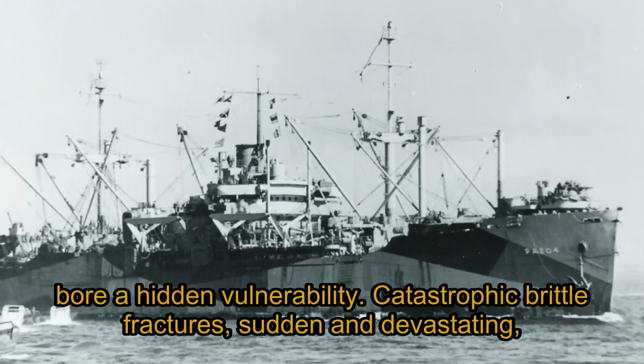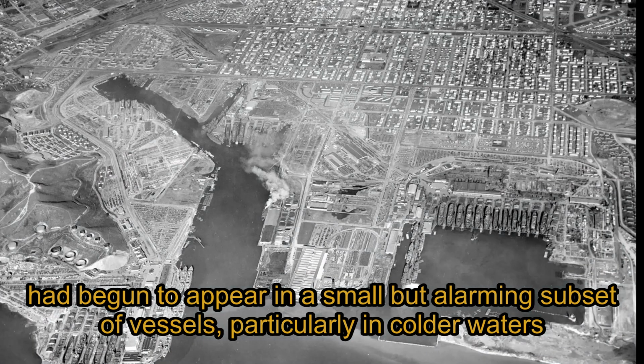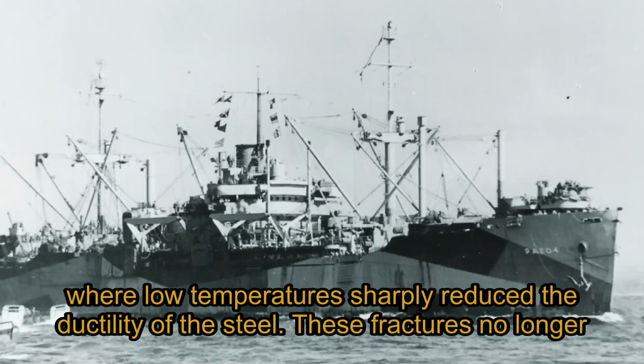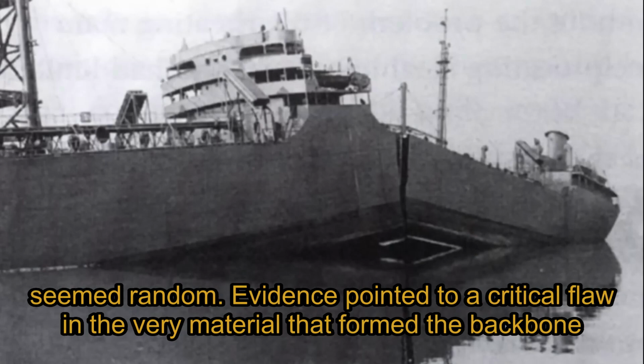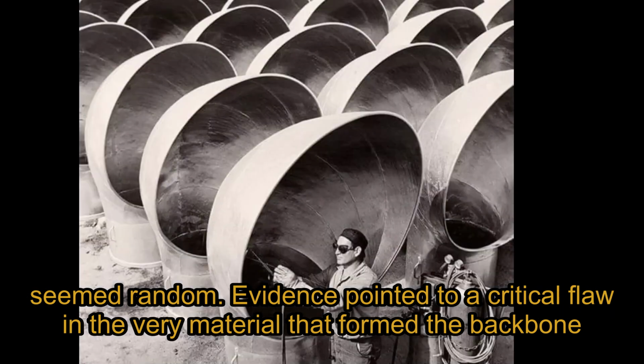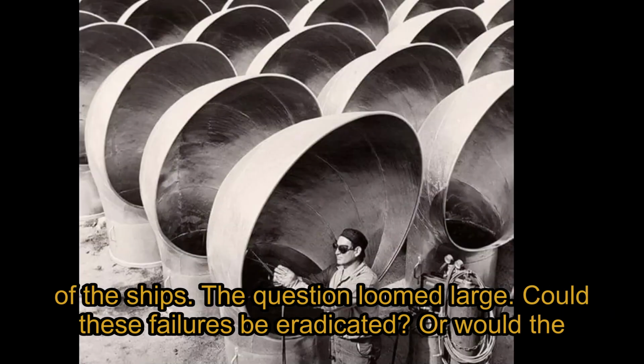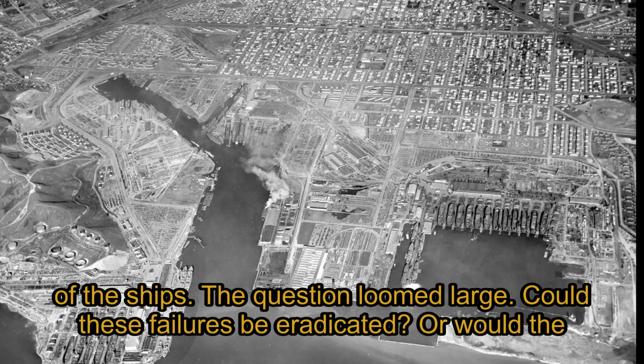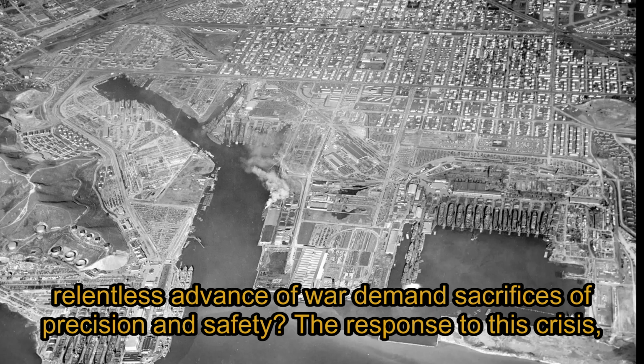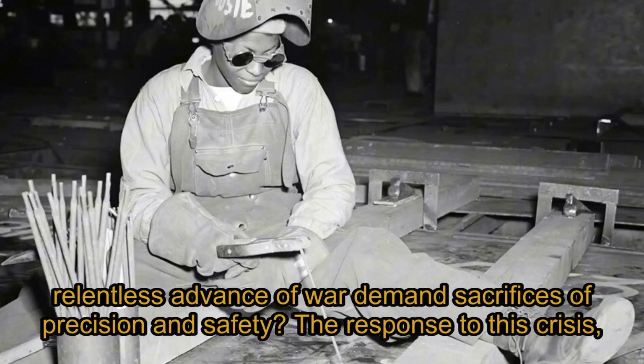Catastrophic brittle fractures, sudden and devastating, had begun to appear in a small but alarming subset of vessels, particularly in colder waters where low temperatures sharply reduced the ductility of the steel. These fractures no longer seemed random. Evidence pointed to a critical flaw in the very material that formed the backbone of the ships. The question loomed large. Could these failures be eradicated? Or would the relentless advance of war demand sacrifices of precision and safety?